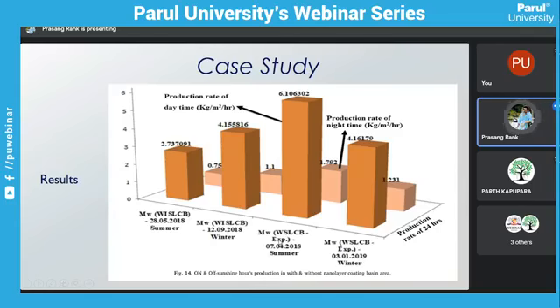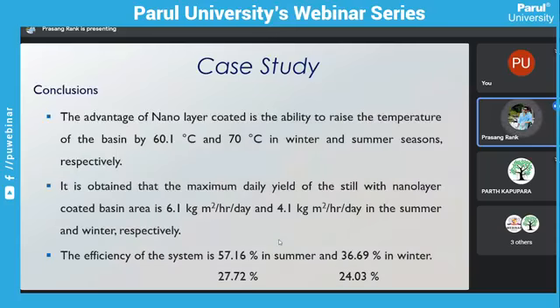So this type of coating material, or anything else, we can use to increase the absorptivity at the bottom. The conclusion of the case study was that the advantage of the nano layer coating is the ability to raise the temperature of the basin by 60.1 and 70 degrees in the winter and summer seasons respectively. So here we can see around 70 degrees Celsius in the summer and 60 degrees Celsius in the winter was achieved due to this nano layer coated bottom.